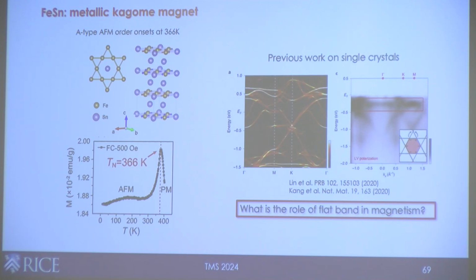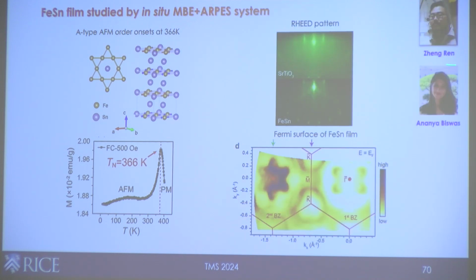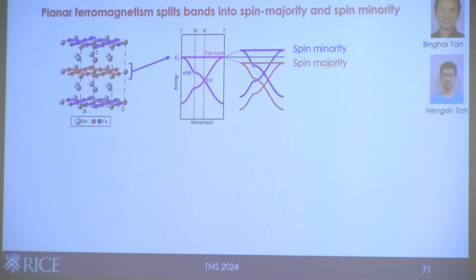So what do we do? My postdoc, Zhengren, who was previously in Ilya Zalkovich's group, is an expert in thin film growth. He built an MBE chamber so that he can grow iron tin films and then directly measure the band structure. And it just turns out that these thin films, for some reason, are very robust. You can crank them through the ordering temperature, and we can still look at the band dispersions over the thermal cycle, so we can actually come to learn about the origin of the magnetic order in the system.